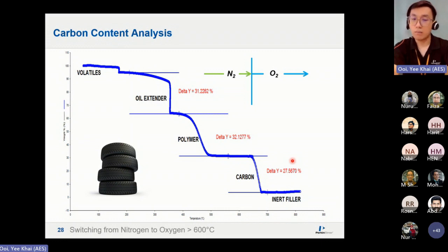But usually what we recommend is after 650, then you switch over to oxygen, because as what I've mentioned just now, most of your polymer will decompose completely after 600 or 650. And then this is a good time for you to switch over to oxygen for the carbon analysis.